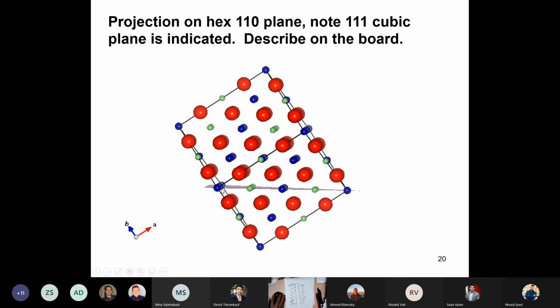But here what you have, it turns out, is a plane that's 3/4 full of lithium and 1/4 full of transition metal, and then a plane that's 3/4 full of transition metal and 1/4 filled with lithium, and that repeats. Okay, so it's really similar to the layered structure, except the metal layers aren't pure lithium and pure transition metal. They're arranged differently.